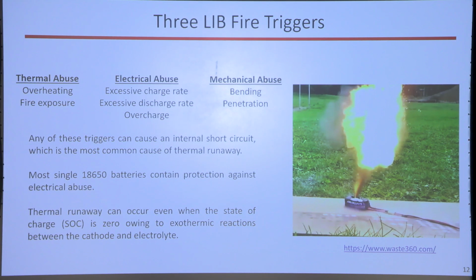Whether it's state of charge of 100, state of charge of 0, it's going to vent and you're going to have a little fire inside your oven. So that's thermal abuse, overheating or fire exposure. And the thermal abuse can happen just from one cell going into thermal runaway in contact with its neighbor.